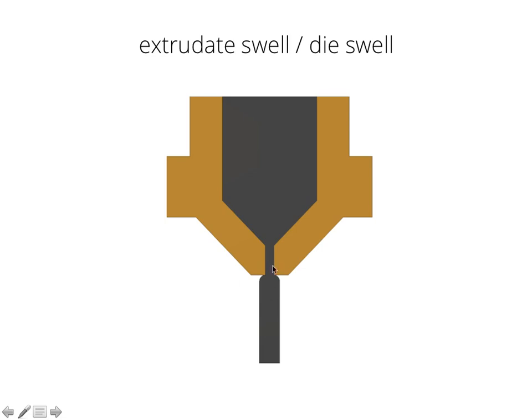So what I did was extrude 15 cm of filament and then measure the diameter of the extruded filament and take averages. Some people will say that extruding into free air means the filament gets elongated as it drops — yes, that's true, but I still think it's a reference worth looking at. I also did not measure the first part where the filament may be overheated; rather I measured the last filament that came out and took an average at certain set points.